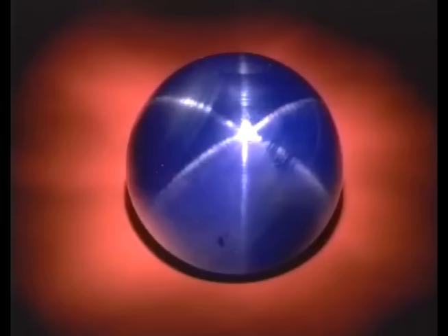It goes back to the early history of when that corundum crystal, when the sapphire crystal was first beginning to form. It was forming at fairly high temperature, typically forms when sort of dirty clays and limestones get squeezed and heated up. As the crystal was growing, the aluminum and oxygen atoms are connecting together to form the corundum crystal, and a few impurities of titanium also got trapped in the corundum crystal. Well, at high temperature, that's not a problem. But as the crystal starts to cool down, it starts to shrink or contract.